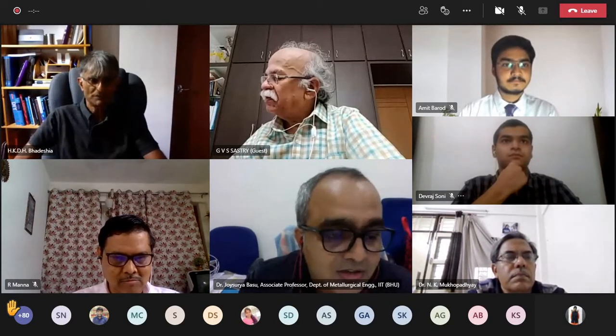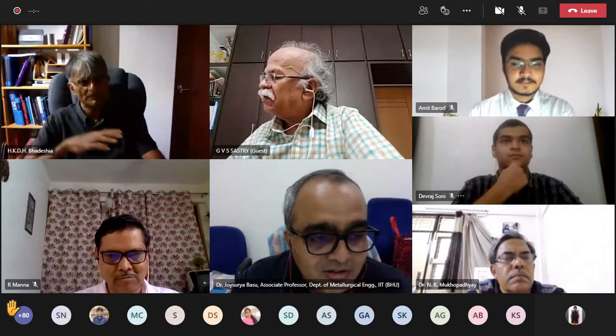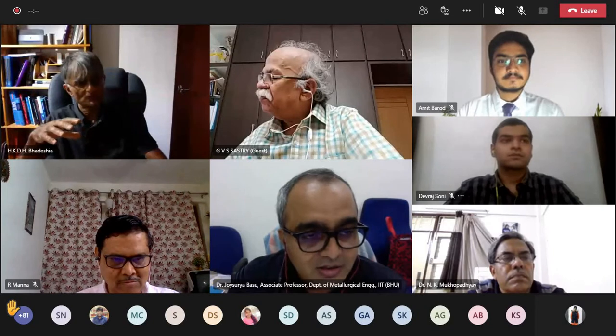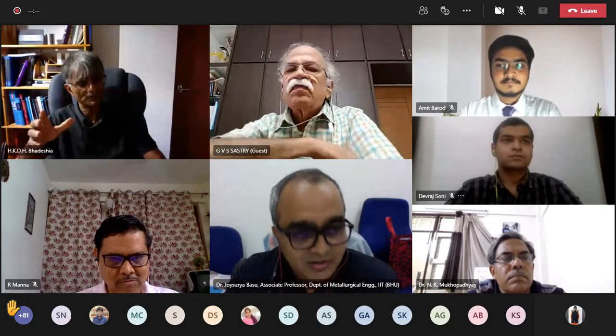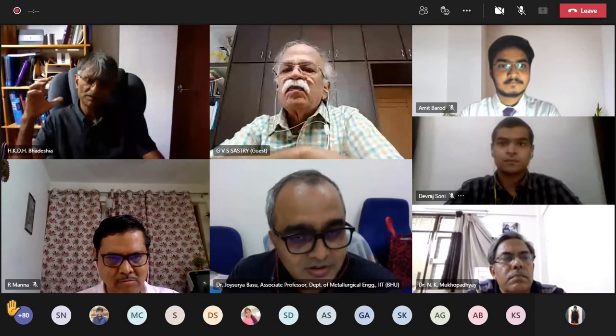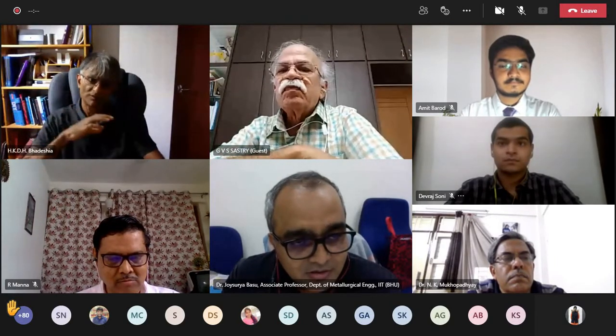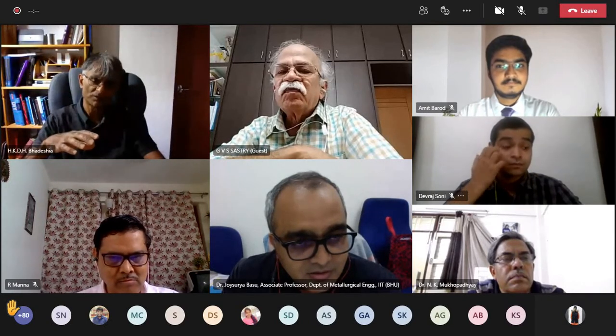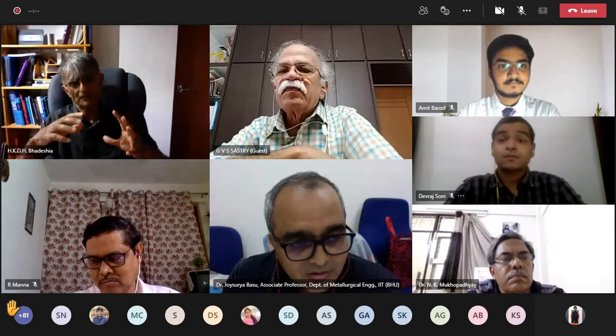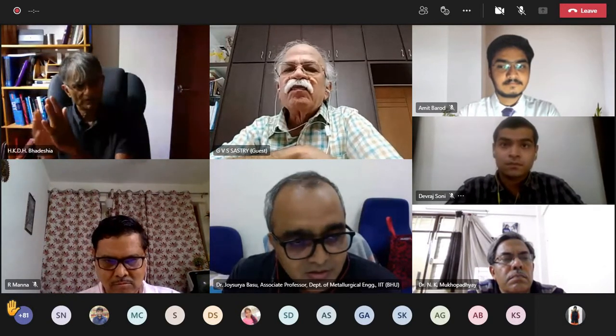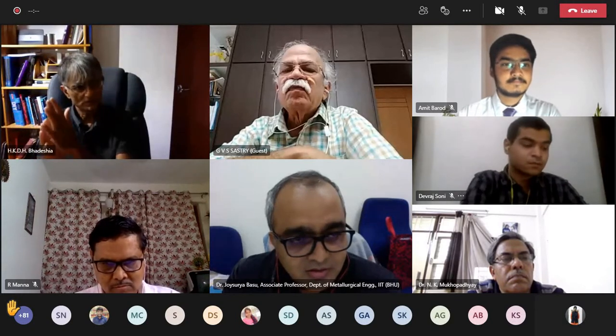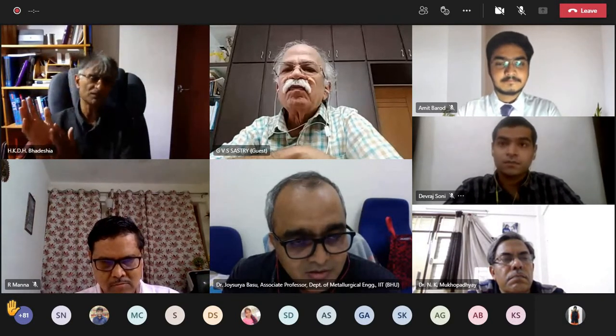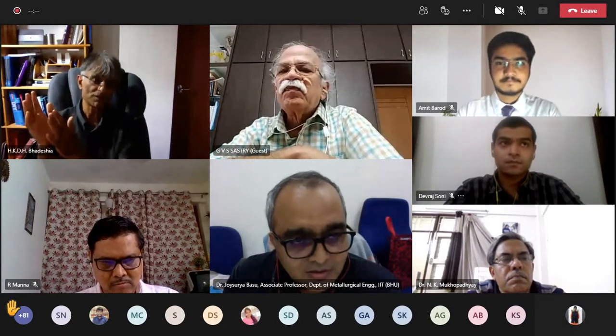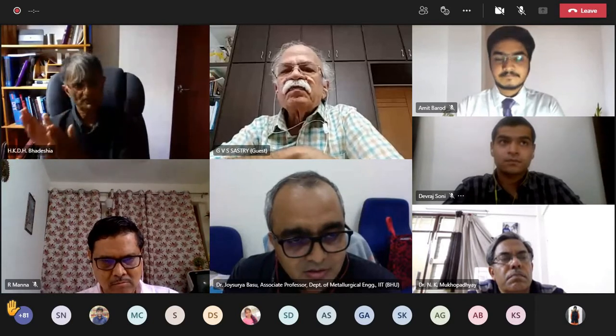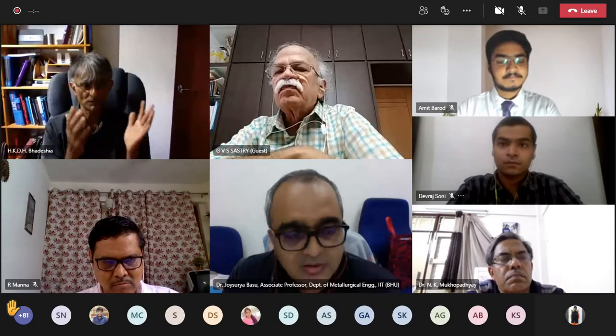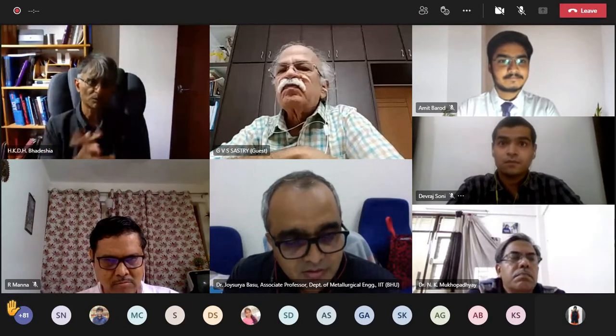It's a very, very good question. The TWIP steels didn't exist when Jack Christian was doing his work, and when Mahajan and Christian wrote that review in Progress in Material Science. But the concept of mechanical twinning, of course, was dealt with incredibly nicely in that review article. Now, it is actually a physical deformation, and it's exactly like martensitic transformation. In the case of martensite, you get a change in crystal structure, but also it's a physical deformation. Now, the twinning shear is much larger than in martensite. It's about 1 over square root of 2, whereas in martensite it's about 0.26.